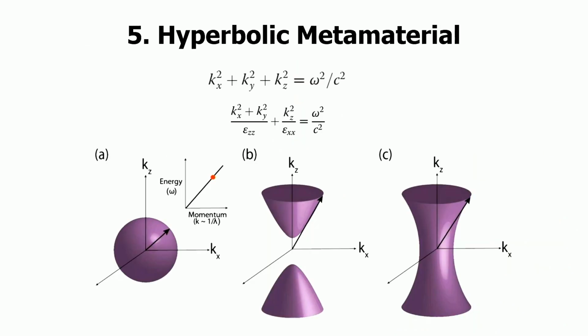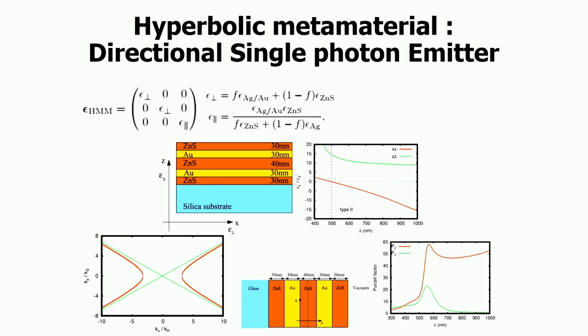So if you have a homogeneous medium, your kx, ky, kz follows the relation given by this because your epsilons are the same in all directions. It's a homogeneous medium. However, if you have a medium where your epsilon zz and epsilon xx, one is positive, the other is negative, then it will have these hyperbolic dispersion profiles, where high k values are also allowed modes in such a medium. The consequences of this I'll show in a little while, but we can design these structures by having layered dielectric and metal structures, and you can get this epsilon perpendicular and epsilon parallel from effective medium theories. And you can calculate the dispersions. One is positive and the other goes to negative values after a certain wavelength region.